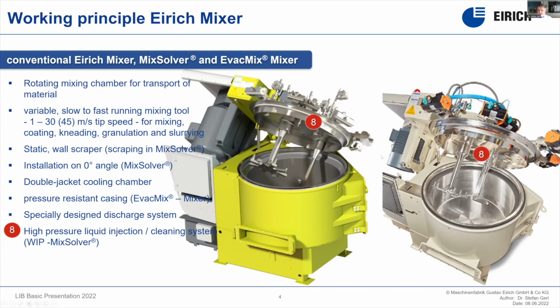For a fully automated plant, we also offer high pressure liquid injection systems, which are used in two ways. First of all, you can, of course, wash out the machine for automatic cleaning. But more important, we add the liquid we have to add anyway into the slurry over these, let's say, different kinds of rotating and static nozzles to make sure that we are always washing away all material which might stick on wet surfaces, like when you're charging the powder and you have a wet cover of the machine, to make sure that 100% of the solids are really part of the slurry and we don't have to interrupt or stop the machine for cleaning. By this, you can save a lot of cleaning liquid, because we keep the machine always clean over the batches, and can make sure that by batch to batch operation, like in the gigafactories, we don't have any changes between the different batches.